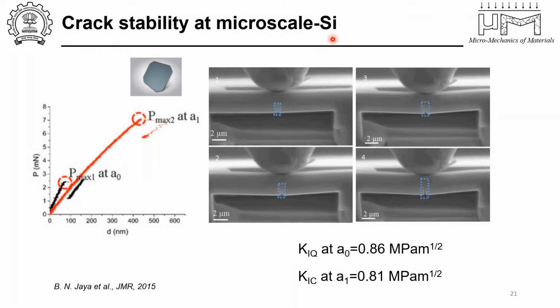Same thing with single crystal silicon. This is what we measured with micron scale specimen. As you can see, there are two different segments. The first loading cycle, the sample undergoes crack growth, so there is a displacement jump.